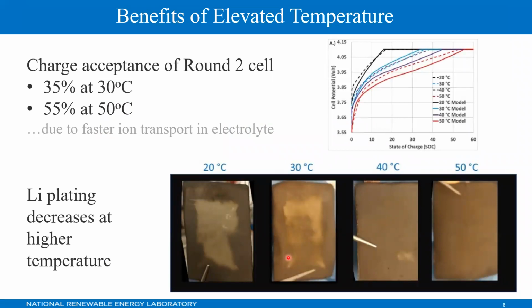To further investigate extreme fast charging enhancement from temperature, a moderate loading cell was charged at 6C for a total charging time of 10 minutes at 20 to 50 degrees Celsius, and the results are shown as dashed lines in the top figure. After the 10 minute charge, cells were discharged at C/2. Each cell was cycled 5 times at one temperature and then cut open in the discharge state to visually inspect for lithium plating. Thus, each charge curve at a different temperature is from a different cell. The final SOC achieved after CC and CV was 16, 36, 38, and 52% SOC. Thus, increasing operating temperature significantly improves high rate charge acceptance.